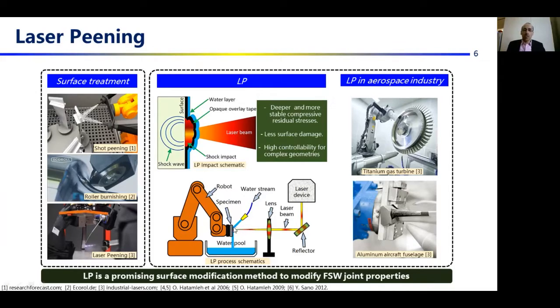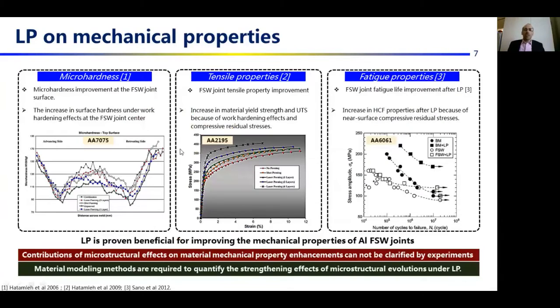The specimen usually is controlled by a robot arm to ensure the uniform laser treatment on the targeted surface. This process has been functionalized in the aerospace industry, such as gas turbines and aluminum aircraft fuselages. Several research works have experimentally investigated the laser peening effects on the aluminum FSW joints, and they have reported the increase in joint surface hardness, tensile properties, and fatigue resistance. So laser peening is proven beneficial for improving the mechanical properties of aluminum FSW joints.